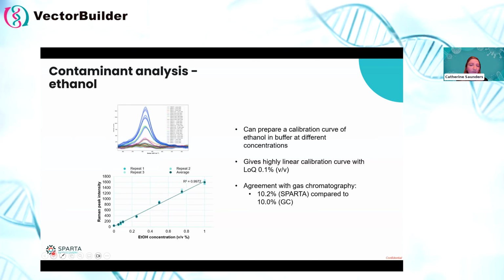So now, because ethanol is in the solution, we can quite readily make a calibration curve of ethanol in the buffer at different concentrations. So what you can see on the top here, this is the main ethanol peak across 3 repeats. And you can see on the bottom, this is then resulting in a highly linear calibration curve. So by analyzing this, we get a limit of quantitation of 0.1% volume over volume.